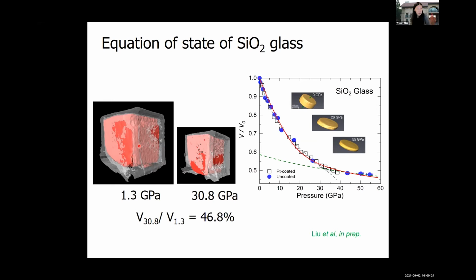And so what Jean found was that between 30 GPa and 1.3 GPa, we saw a volume reduction of 2-fold. We became pretty concerned that the platinum layer might be changing how the volume changes with high pressure, influencing the equation of state. So we also just cut discs of SiO2, where the disc is about 15 microns thick and 40 microns in diameter. And he tried imaging that without a coating. That actually also worked pretty well. So both the uncoated and coated results give pretty consistent results. And there's a change in compressibility at 30 GPa in our SiO2 results, but we're still working on that, and also some other silicate glass work.